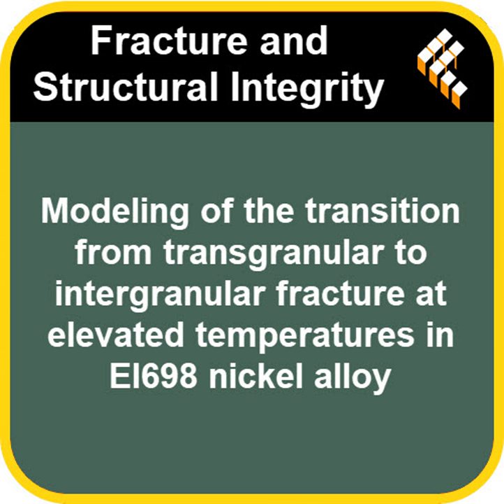Okay, so summing this up. What this research really presents is an efficient computational method using this new custom finite element for phase field fracture modeling. It successfully accounts for that crucial decrease in the critical energy release rate, Gc, with temperature. And vitally, it incorporates the critical role of energy dissipation during plastic deformation, distinguishing bending from breaking. And the bottom line is, the results seem to correlate very well with previously conducted fractographic studies, those detailed analyses of actual fracture surfaces. It feels like a significant step forward in predicting how these critical parts might fail. I think that's a fair assessment. It provides a robust and computationally feasible tool.